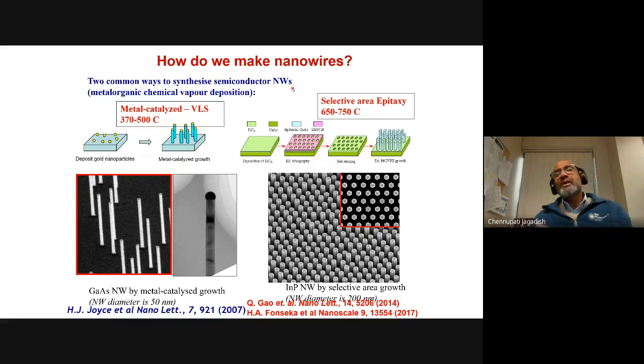There's an alternative technique called molecular beam epitaxy, MBE. You can use either of the techniques depending on your own choice, and we happen to have MOCVD reactors, so we try to use those for growth of these nanowires. So in the case of the metal catalyzed VLS growth process, we typically take nanoparticles of gold, for example. In this case, I'm showing an example of 50 nanometer gold nanoparticles. These come in a colloidal solution. You put a droplet of that there.